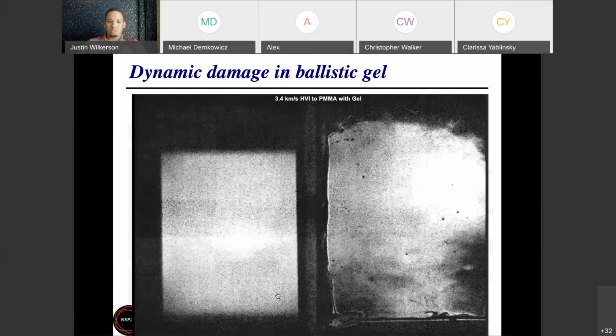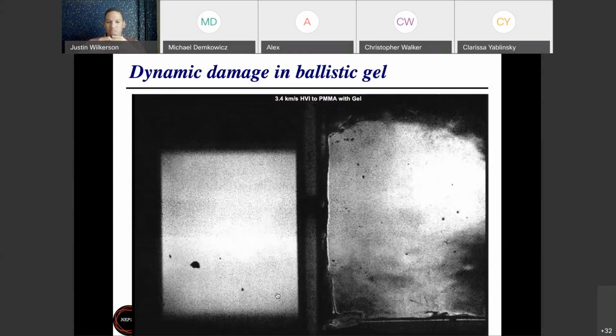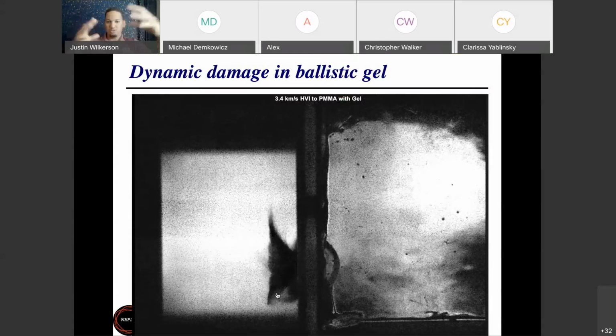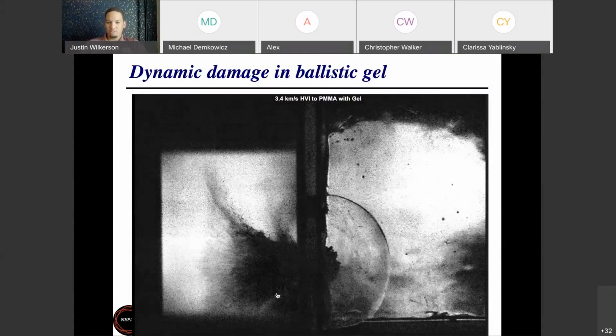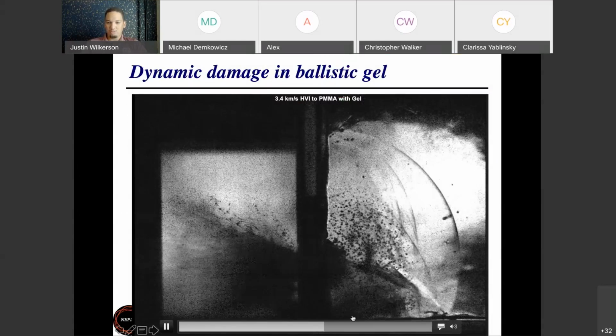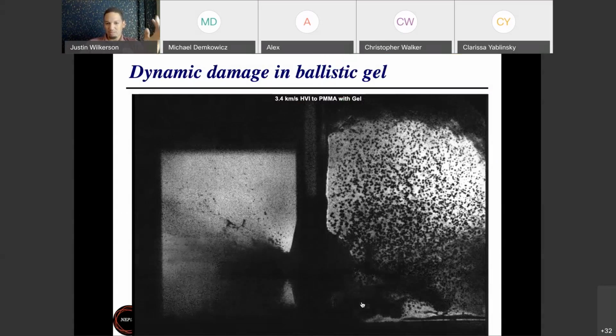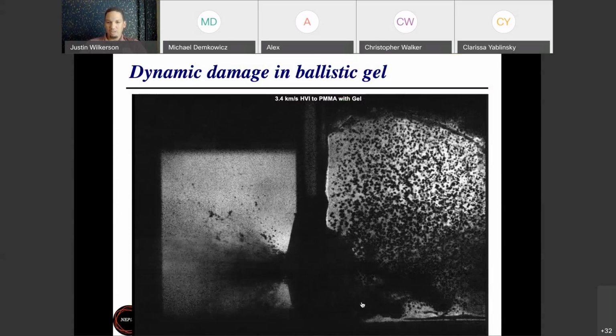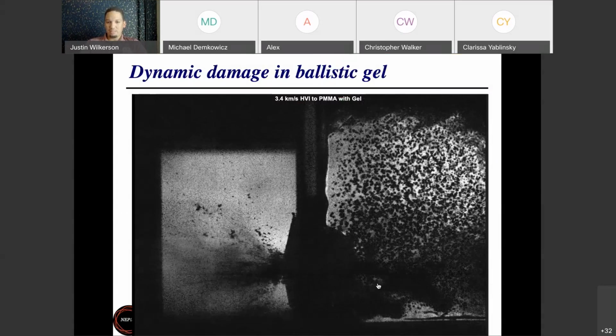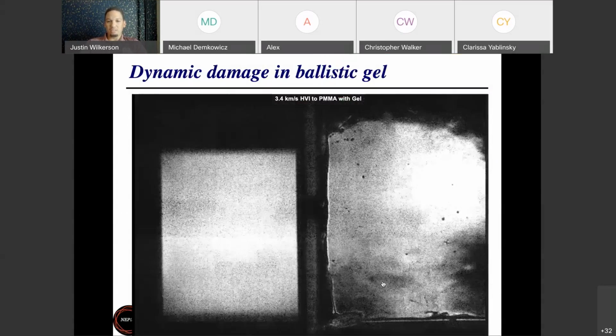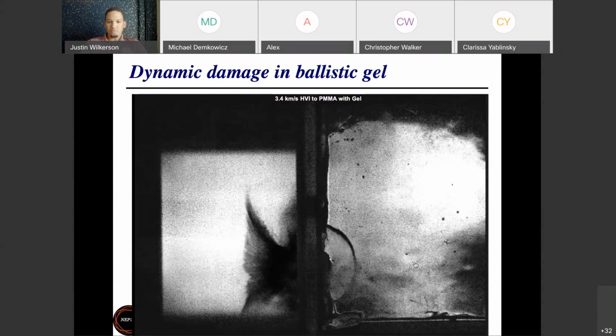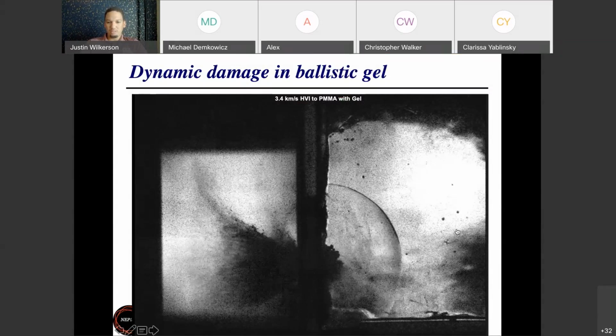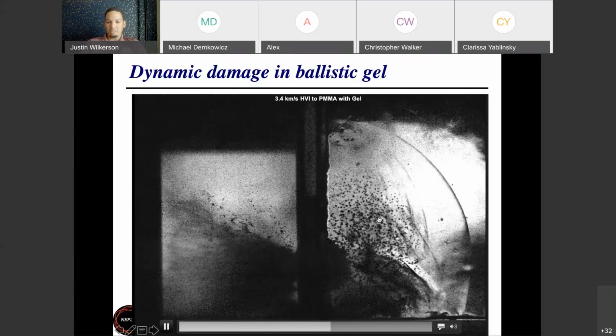Okay, and then you're going to be able to see a fairly semi-hemispherical shock wave moving out. It's going to hit the boundaries and cause reflection waves that come off. Those reflection waves are going to take the material from a nominally compressive state into a tensile state. And when it goes into that tensile state, it causes cavitation of the gel. So void nucleation inside the gel. And so all these black splotches that you see showing up are cavities forming inside this ballistic gel.